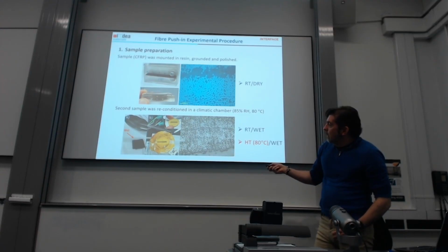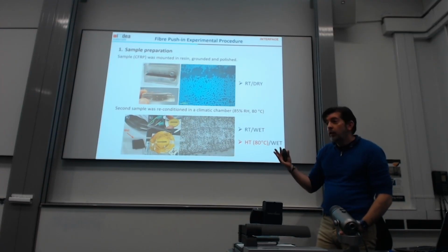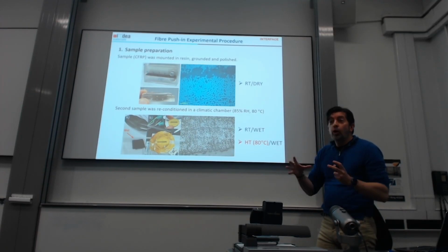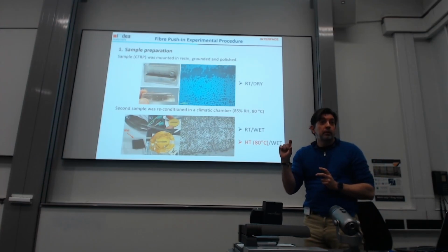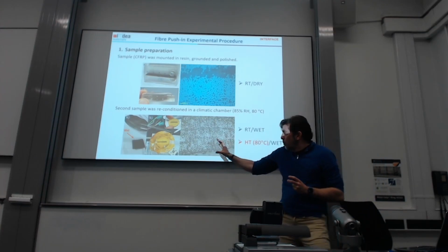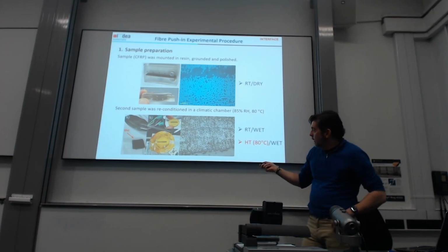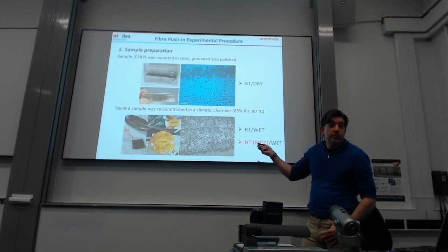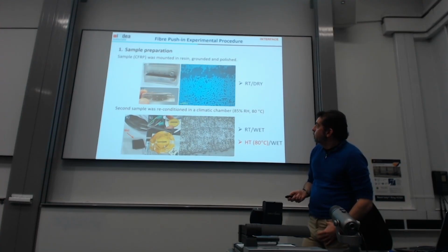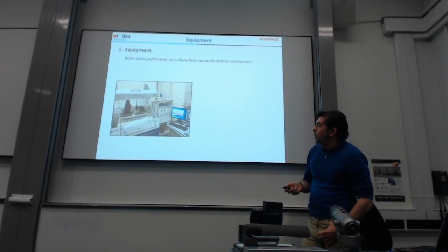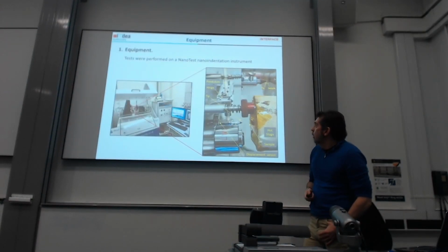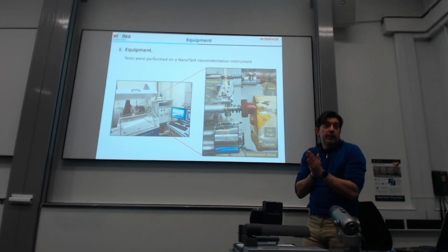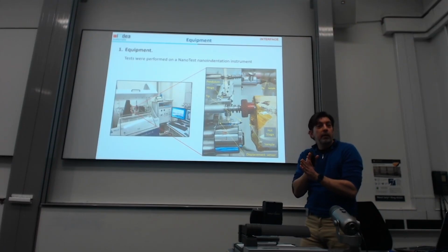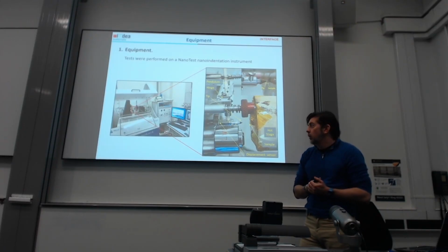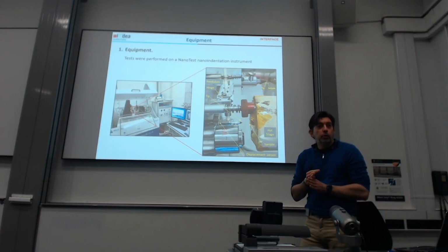So we mount the sample in the hot stage. A good thing about the NanoTest is that it can accommodate large samples. So we can just place the sample there, and the important thing is that we can see the fibers. For this one, we use our NanoTest Platform 3. And a good thing about it is we can heat the sample and the tip independently, and we can carry out the test with the necessary loads for the pushing.